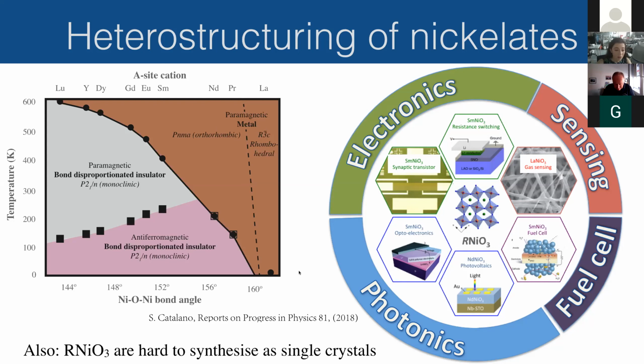One other pragmatic point is that rare earth nickelates are really hard to synthesize as single crystals. Now people are making a bit of progress. Seems to be okay for the ones that are the least distorted. But for a very long time, it was not possible. So this is why studies of the rare earth nickelates really focused on heterostructures for most of the time.